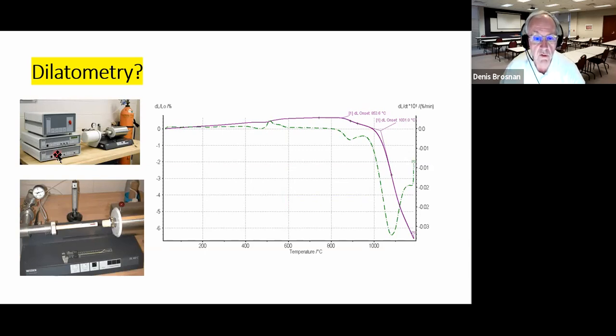So here's a device for measuring thermal expansion in my lab. This is our research grade dilatometer made by a German company, Netzsch. And here's the furnace right here. In the lower picture, you can see the furnace. There is a ceramic tube that holds the specimen. There's a push rod inside the tube where the length of the little specimen inside here, which is typically, in our case, about 20 millimeters in length by about 4 millimeters in width and breadth. So nevertheless, a small specimen is used.